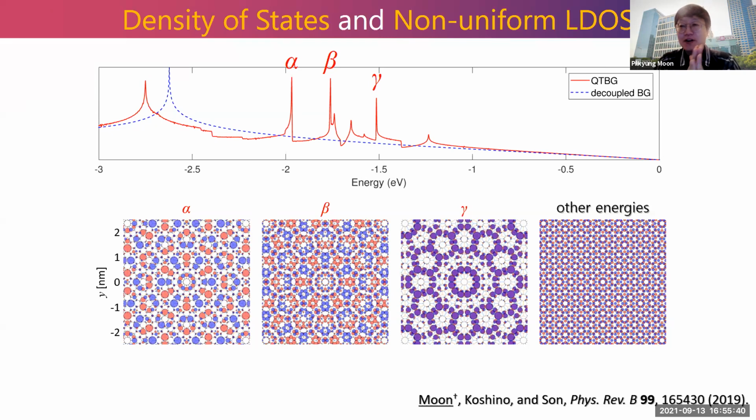Almost similar. I first expanded this to a 4-dimensional structure. Although this is a 2-dimensional structure, it has a 4-dimensional subspace. So I first found the subspace spanned by the Hamiltonian in a 4-dimensional space, but soon found that this can be reduced to a 2-dimensional structure because of the unique situation of this 2-dimensional van der Waals quasi-crystal.